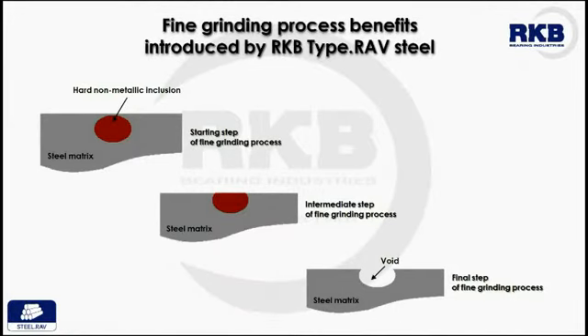One of the major disadvantages of using standard steel is evident during the fine grinding process. In fact, in this phase, the softer steel matrix surrounding the hard brittle non-metallic inclusions is partly removed. The removal of the inclusions from the steel surface forms a void cavity or a pit. With time, during bearing functioning, this void can react as a micro-crack initiator that finally may lead to the total bearing failure. On the other hand, the RKB Type.RAV steel has a high cleanliness as regards non-metallic inclusions, which decreases the possibility that during the fine grinding process void cavities form.